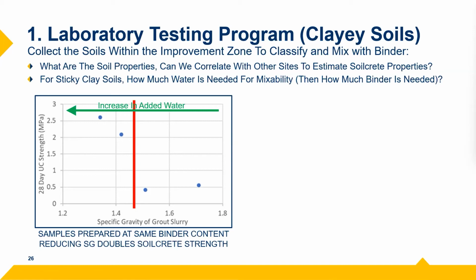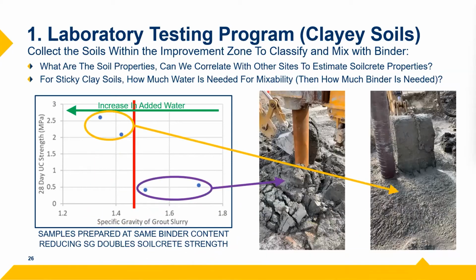And so it's much easier for us to add a little bit of water and much more environmentally sustainable to add that little bit of water than it is to start adding more and more and more cement until we finally get what we need. And you can see how that kind of correlates with how the soilcrete works. If we're not adding enough water, if the grout's at a real high specific gravity, again, we kind of get this chalky material. It's going to be difficult to mix. It's going to be difficult to sample. So we would expect strengths to be a little bit lower. And then as we get that better mixed material, as we get a little bit more moisture in the grout, it's easier to sample, it's easier to mix, and we get this better quality.